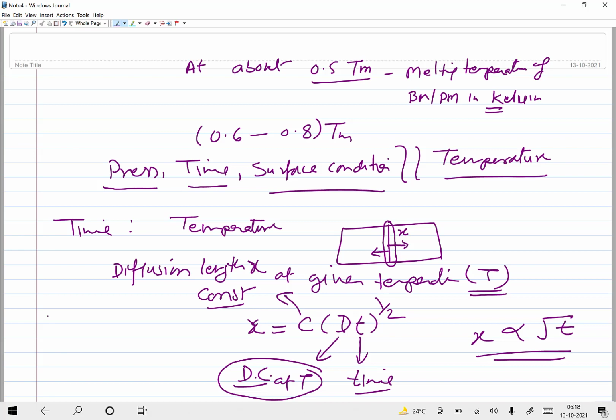So if we see here, diffusion coefficient is found proportional to, or you can say varies exponentially with the temperature, while the diffusion length is proportional to the square root of the diffusion time. So the diffusion based reactions progress with the square root of the time, whereas these reactions will be progressing exponentially with the temperature, as a function of temperature.